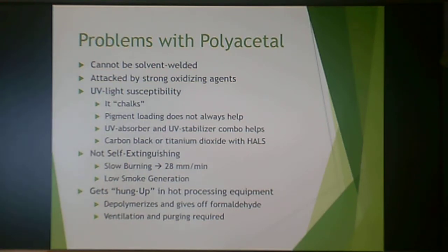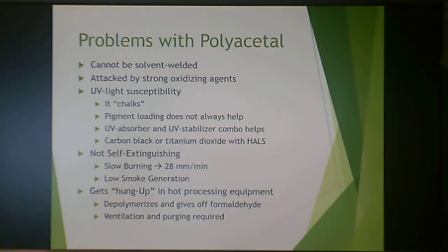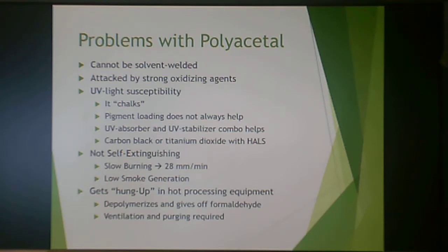However, polyacetal has some problems. Because it is very crystalline, it cannot be easily solvent welded. It can be attacked by strong oxidizing agents and has UV light susceptibility, causing chalking — a white film on the surface after UV exposure. Loading with pigment, carbon black, or titanium dioxide with a hindered amine light stabilizer can help, but doesn't always work well. It is also not truly self-extinguishing, though it burns very slowly with low smoke generation.